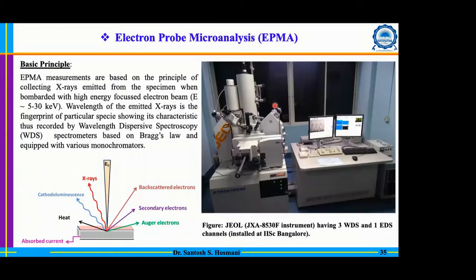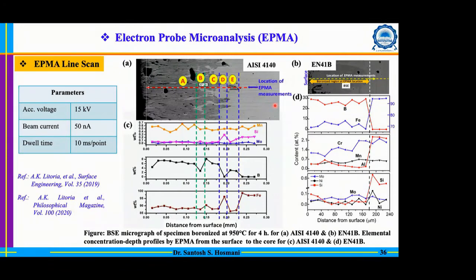Now we did an EPMA analysis. I will not go into the mechanism of EPMA, as you're already aware of it. This is basically the chemistry. To understand the chemistry of these boride columns, we did the analysis point by point within the boride column as well as in the matrix. Here you can see something interesting: we have very high boron content, already reflected here. And for silicon, the content is almost 0 in the boride region. That means the solubility of silicon is 0 in this boride column.